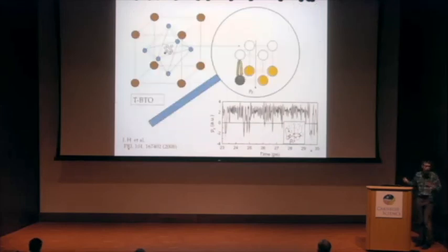So we are in the tetragonal phase. We can think about eight minima around the center of the oxygen cage. Four of them are occupied because we are in a single-domain tetragonal phase. But from time to time, the polarization oscillates up and down, and sometimes it goes to a position where there is another minimum, which is no longer occupied. So on average, the other four sites are also a little bit occupied. This is what we can see in simulations.